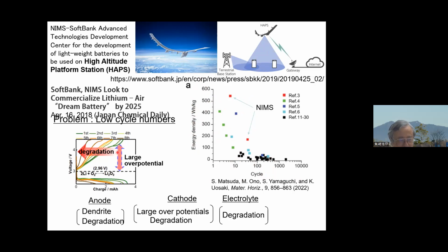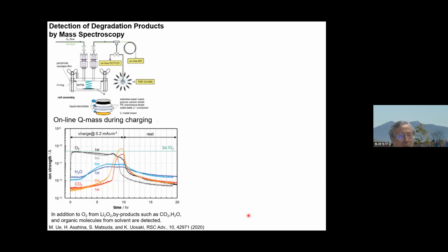There are lots of problems. Anode side, metal electrode, we have dendrite formation, degradation of metals, large overpotential, degradation of the cathode, and the electrolyte itself degrades. So far we have worked on the cathode and electrolyte degradation by using various techniques. One is the mass spectroscopy in situ, real time. In this case, the cell is quite similar to the real cell. We have a very small amount of electrolyte and lithium metal combined together within this cell. And then we analyze the decomposed gas by online mass spectroscopy.